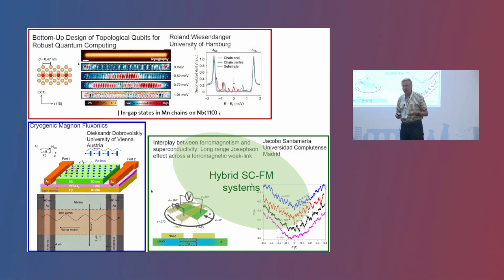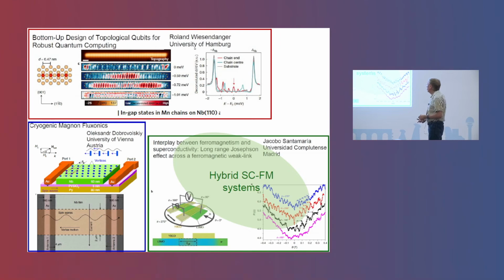So the idea was that as soon as one has a vortex state in a superconductor, which is a kind of periodic topological lattice, and one puts it into contact with a ferromagnet, then if one matches the periodicity of the spin waves excited in this ferromagnet with the periodicity of the vortex lattice, they should interact. And in this work, Oleksandr Dobrovolskiy from the University of Vienna has shown that indeed they can bring this vortex lattice and the spin waves into that regime where they start interacting.